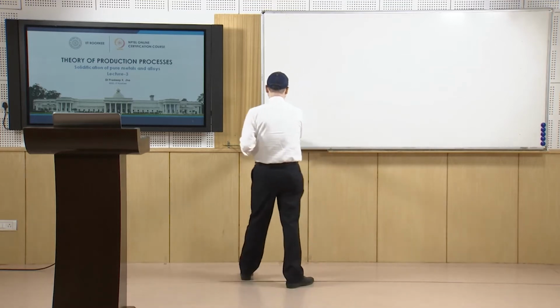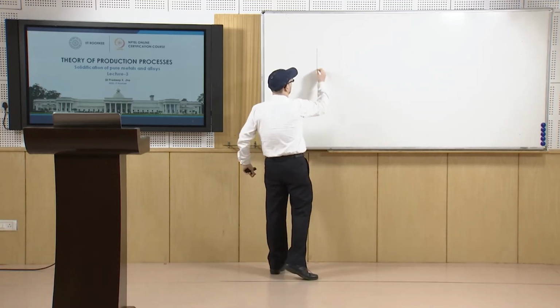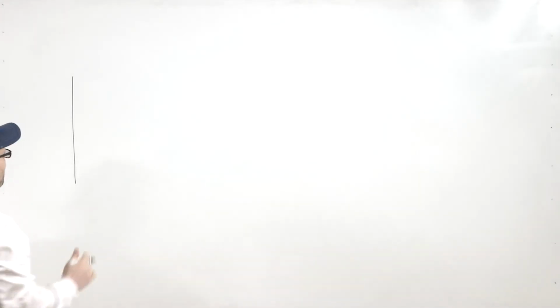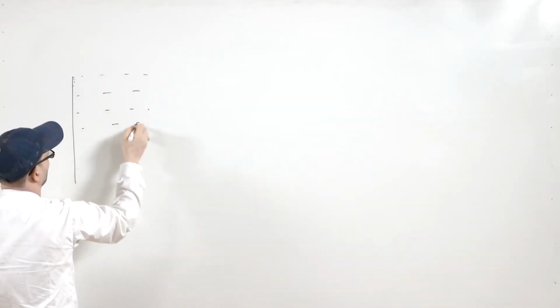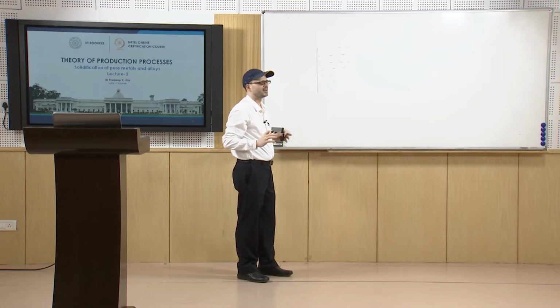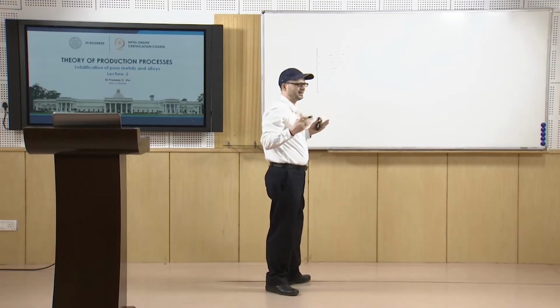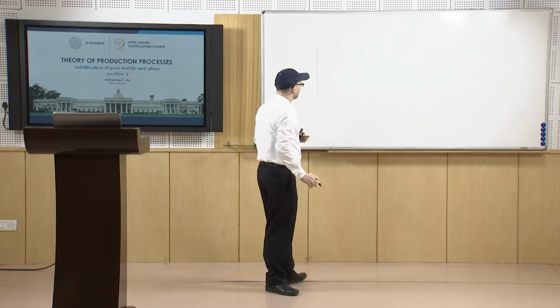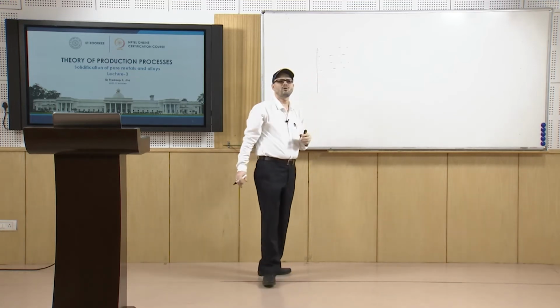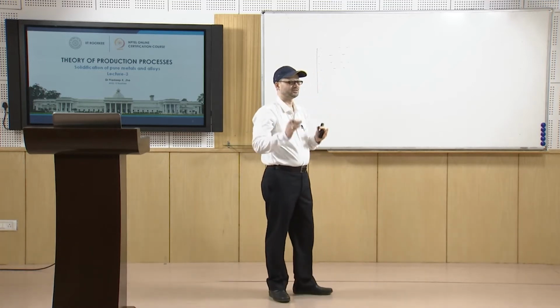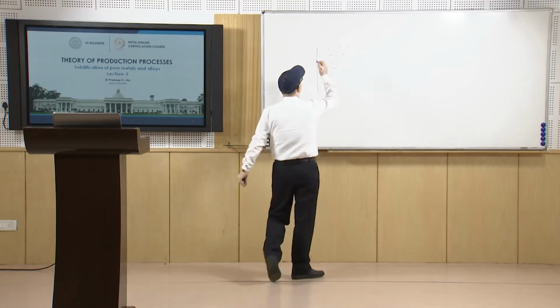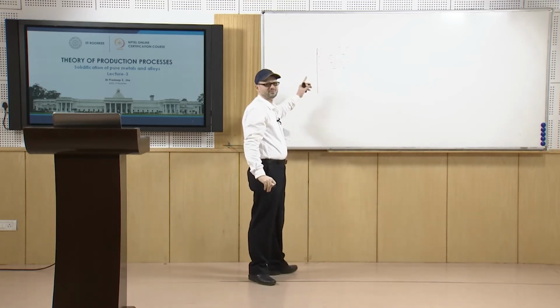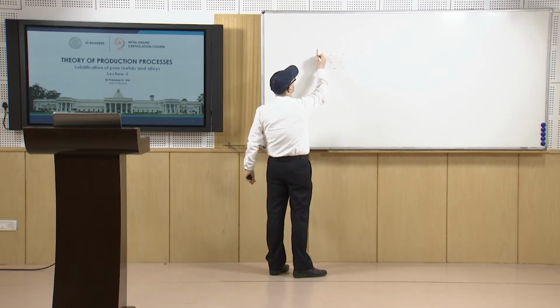As we see, once you have the liquid touching this boundary, and here everywhere is liquid, basically all is liquid. So, once it touches this boundary, if there is heterogeneous nucleation condition, and practically that is so whenever we cast any material, then if this is the mold wall, it is at lower temperature and has many sites where the nucleation starts. If the nucleation starts here and the largest undercooling is felt here, then, as we had discussed, you have initial solidification happening here.